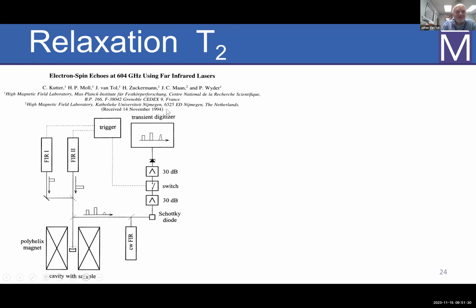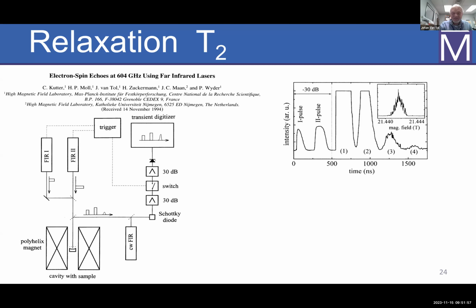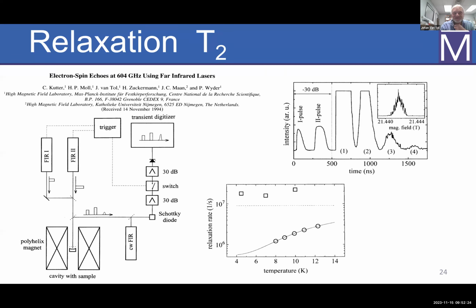It was quite an interesting experiment in the sense that we had two FIR lasers. So these are CO2 laser pulsed molecular gas lasers that provided us with the frequency at 604 gigahertz. And we actually got it to work thanks to the persistence of Christoph Kutter, the grad student. He now is, I think, the director of the Fraunhofer Institute for Microelectronics. But we did find that we could do pulsed EPR. So this is actually a BDPA sample. It is quite a concentrated BDPA sample, I must confess, but you can see that the echoes themselves give their own echoes again. We got up to 4 echoes in this particular system.